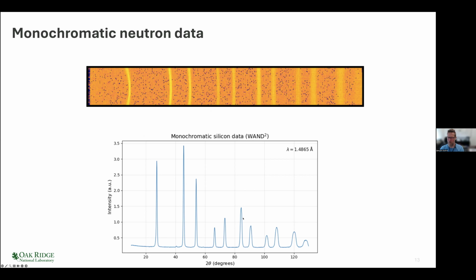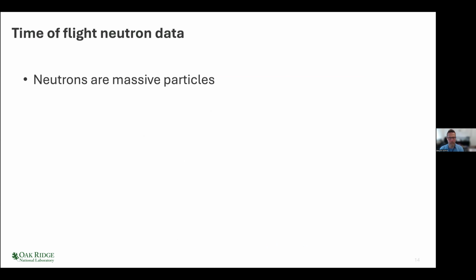The only thing that looks probably a little bit odd is the Debye rings extending out to such high angle that they become essentially vertical. This is about 90 degrees somewhere here. So this detector is spanning an arc rather than being a flat sheet as you would typically measure X-rays. But it gets a little bit more complex if you go to the time of flight technique. And the time of flight technique is using not a monochromatic beam, but a white beam.